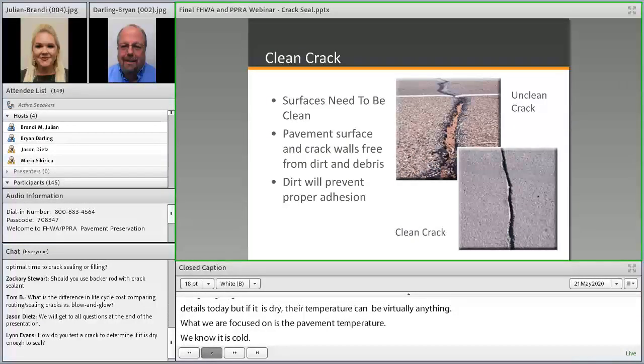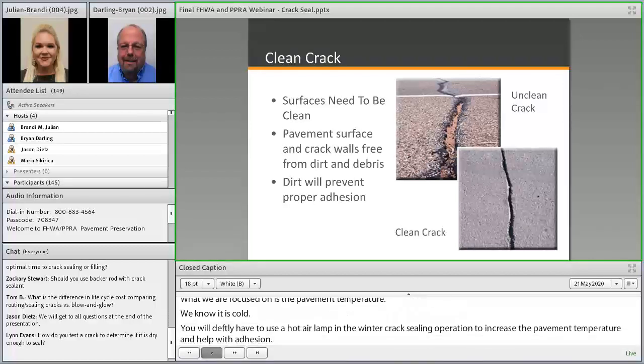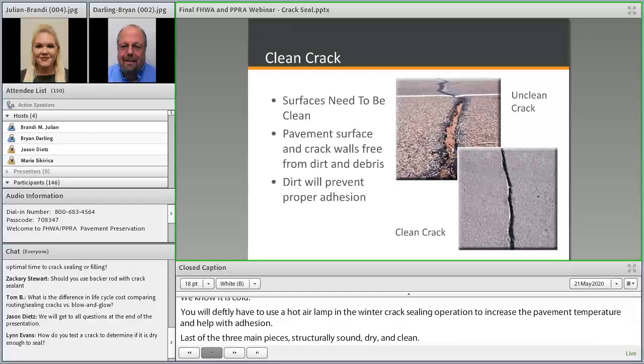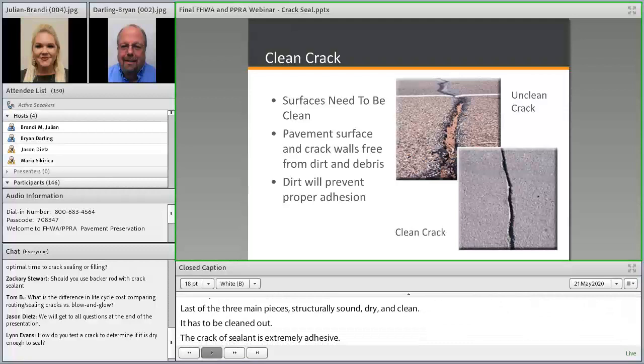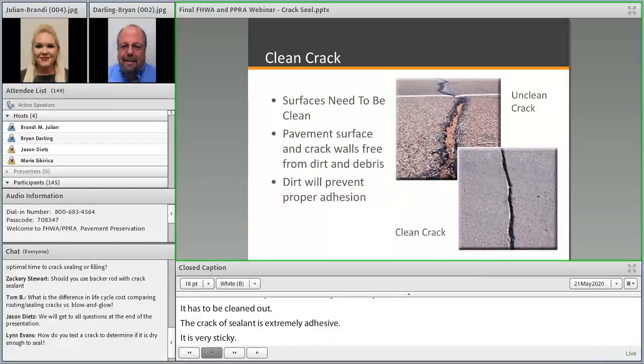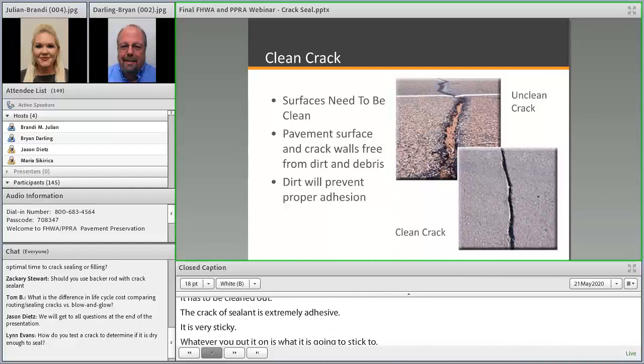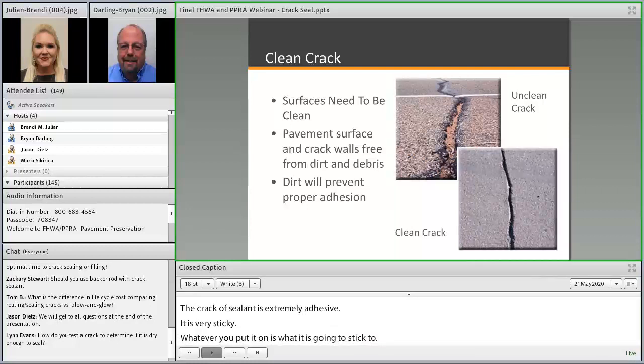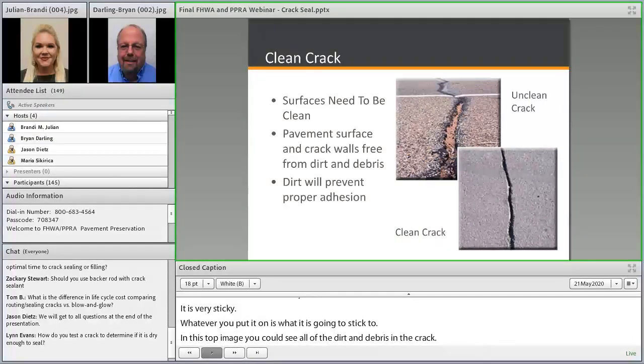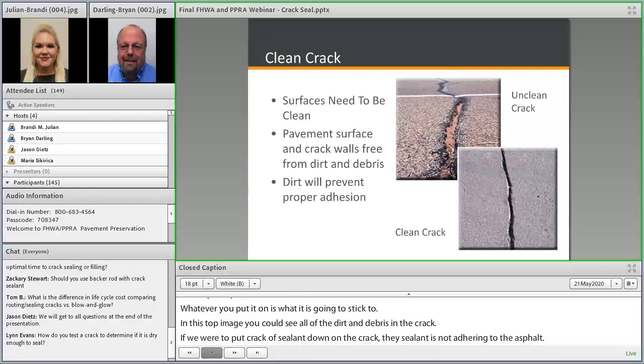And then last, again, of the three main pieces: structurally sound, dry, and clean. It has to be cleaned out. Crack sealant is extremely adhesive. It's really sticky. Whatever you put it on, that's what it's going to stick to. So in this top image here, you can see all the dirt and debris down in that crack. If we were to put crack sealant down on that crack, the sealant is not adhering to the asphalt. It's sticking to that dirt in the crack. And after that sealant cures, you'll be able to walk over, bend down, and pull that right out of that asphalt. It's not going to do what we're intending it to do.